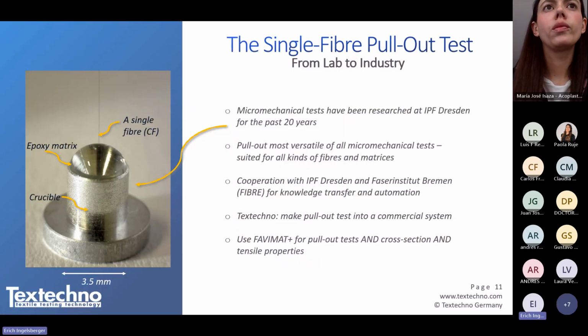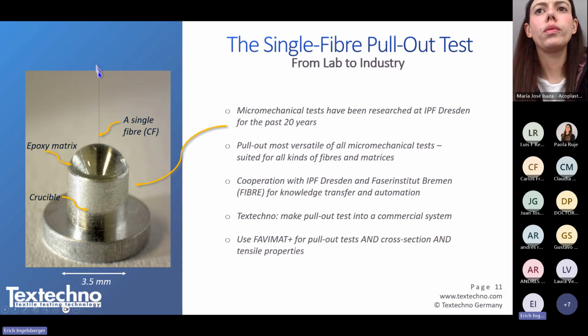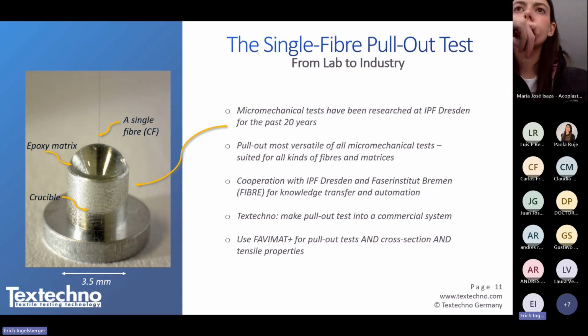Here on the left-hand side, you see a test specimen which we produce using one single fiber, which is embedded into a drop of matrix. In this case, it is carbon fiber with an epoxy matrix, thermoset. This crucible is about 3 millimeters, very small. That means the drop of matrix needed is extremely small, about 2 microliters. This means producers of such matrix systems can synthesize only a very small amount of matrix to analyze.